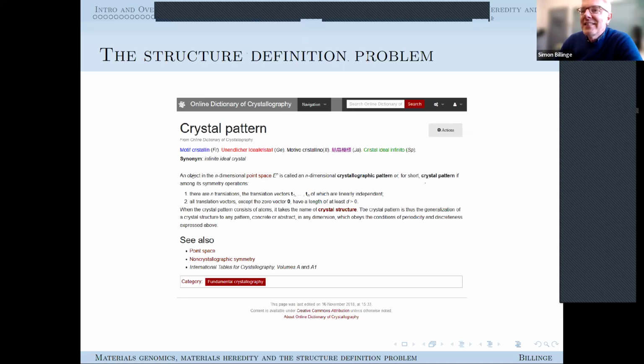The definition of crystal pattern: an object in the n-dimensional point space E^n is called an n-dimensional crystallographic pattern, or for short, crystal pattern, if among its symmetry operations there are n translations, the translation vectors t_1 up to t_n of which are linearly independent, and all translation vectors, except the zero vector, have a length of at least d greater than 0. So this is rigorous, it's mathematical, it's well-defined, but functionally it's completely useless, right? Because it doesn't help me answer the question of whether FCC iron and FCC nickel are the same structure or not. Well, actually what this tells you is that they're not, because they're going to have different sets of translation vectors. But yeah, it's functionally not a very helpful definition of structure, I would say.